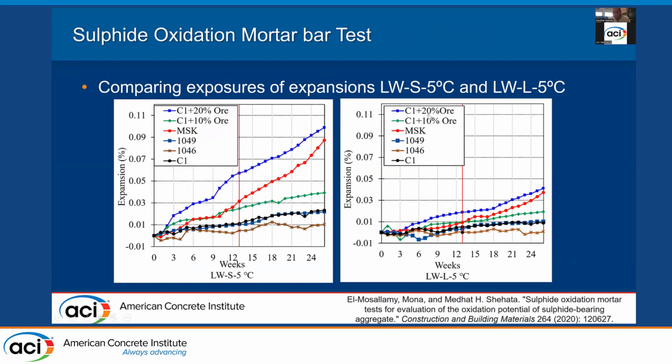So we continued, we ran the test. And these are the results. Again, the siliceous aggregate or non-carbonate aggregate that used to show expansion, they are at the bottom here. What you see here is our Maskimo, the one from Trois-Rivières. And these are actually blended. So that's control aggregate, non-sulfide aggregate blended with the ore. Again, because of the lack of sulphide-bearing aggregate, we had to mix the ore with non-sulfide aggregate. So you can see a good discrimination here, high expansion in case of sulfide aggregate, non-sulfide, very low expansion.